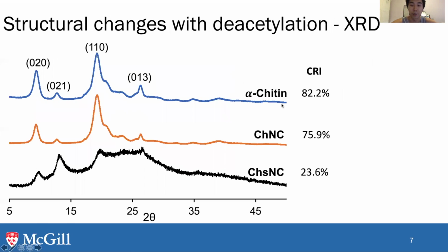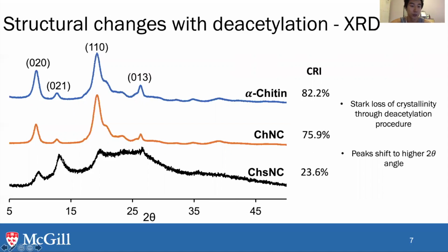So on the top here, we see our bulk chitin in the alpha crystalline polymorph. We can see the reflections here. And once we go into the chitin nanocrystal, you can see that the overall peaks remain the same. However, once we go into chitosan, this is where we see a lot of change. So we can see that we have a highly amorphous region here. If we calculate the crystallinity index in all of these, you can see that going from chitin to chitin nanocrystal doesn't really change. However, once you go into the chitosan nanocrystal, this is where a stark decrease in the crystallinity occurs. And moreover, if you look at the peaks here, these peaks actually shift to a higher 2 theta angle, meaning that the lattice parameters within these crystals are changing themselves during this deacetylation step.